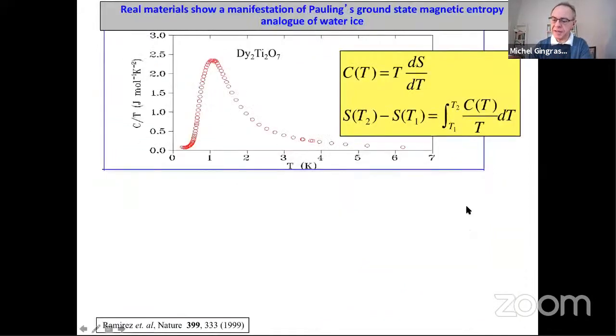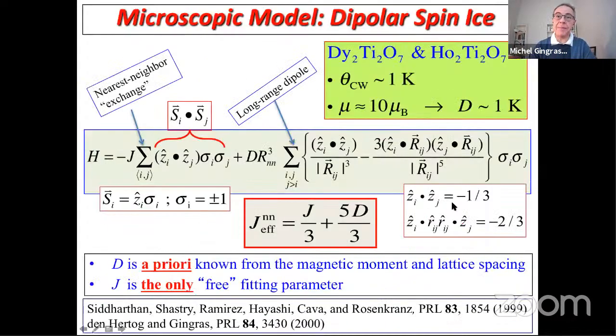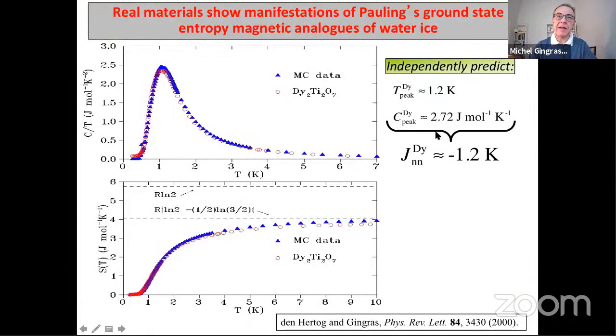So the frustration in the system comes from the dipolar interactions, and they correspond to the largest energy scale in the problem. This creates a paradox that took a long time to resolve. These dipolar interactions are infinite range. They are not nearest neighbor. There are many sublattices that get involved as you go further and further from a given site. So it's a very complex interaction.